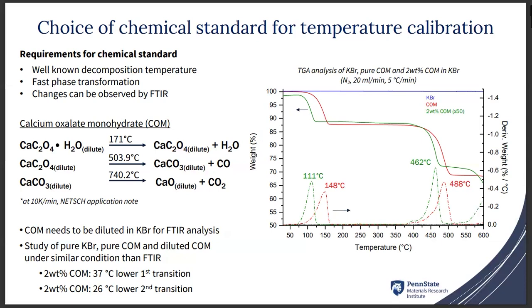We analyzed the pure calcium oxalate monohydrate, and we saw the first event at 148 Celsius and the second event at 488 degrees Celsius. Then we decided to look at the diluted sample because by FTIR we want to use a diluted sample to avoid saturating the detector. We looked at 2% calcium oxalate monohydrate, and we can see a shift of the temperature at which it reacts. We also studied pure potassium bromide, and nothing happened, meaning the only thing we're seeing is from the calcium oxalate monohydrate in potassium bromide. So now we know the two transition temperatures, 111 and 462 degrees centigrade.